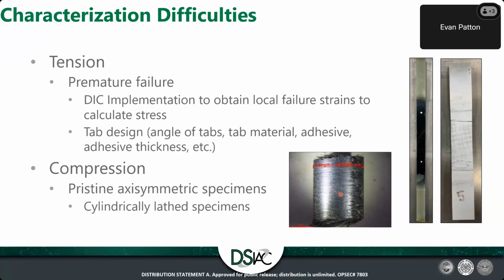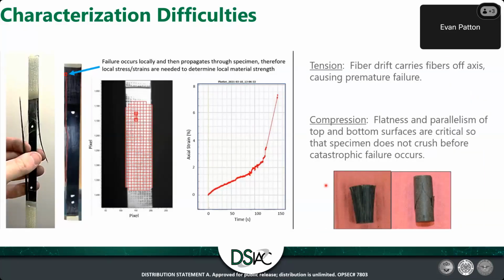So to do that, we chucked it up in a lathe just to see how the material would machine down. And we got a really good surface finish on it. It actually machined quite well and led to some good representative samples, which I guess since we're talking about them are shown here on the bottom right. These are failed specimens. The one on the left, the fibers are going up and down, and the one on the right, the fibers are essentially coming at you if you're looking at your screen. So we were happy with these failure modes.